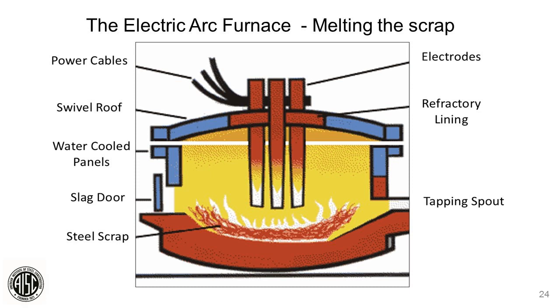Well, to contain this, we have a refractory roof that swings off so we can put the scrap in with the electrodes. We have water-cooled panels in the upper half of the shell that basically take some of the heat away so we don't melt the furnace down. And then the bottom half is all refractory lined with dolomitic type refractory. The scrap is in the middle.